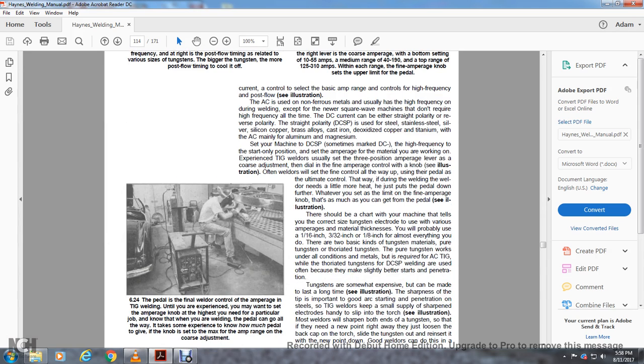See the illustration. There should be a chart with the machine that tells you the correct size of the tungsten electrode to use for various amperage and material thickness. You probably use 1/16, 3/32, or 1/8 inch for almost everything you do. There are two basic kinds of tungsten material: pure tungsten and thoriated tungsten. Pure tungsten works under all conditions and on all materials, but is required for the AC TIG, while thoriated tungsten is used for direct current straight polarity welding, often because it makes slightly better starts and penetration.